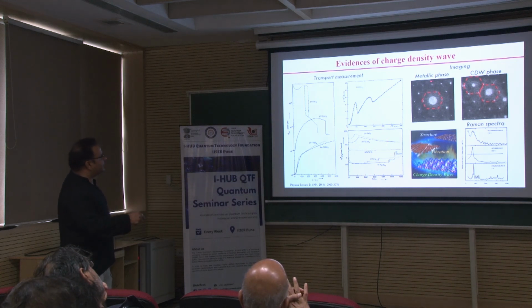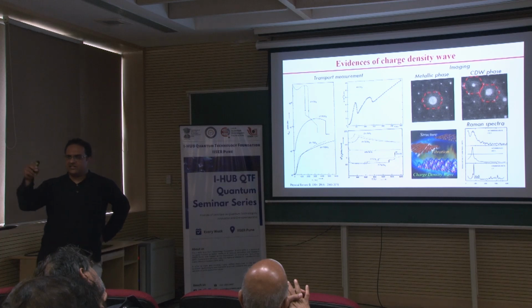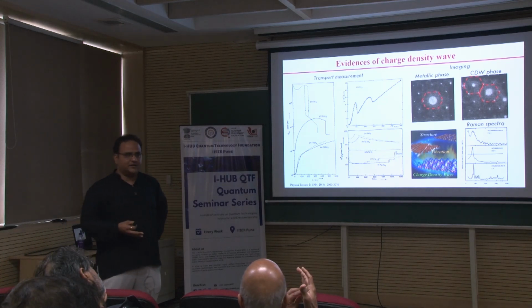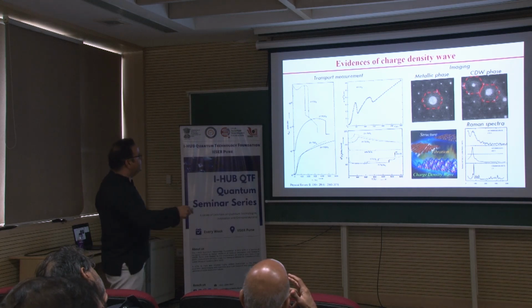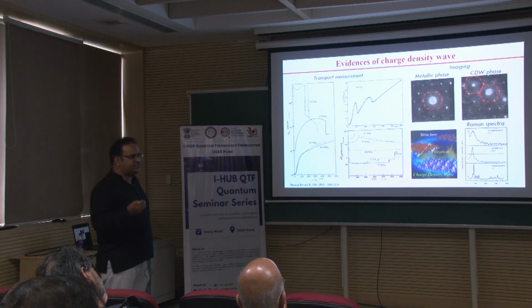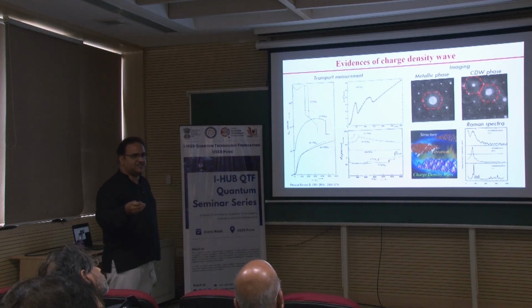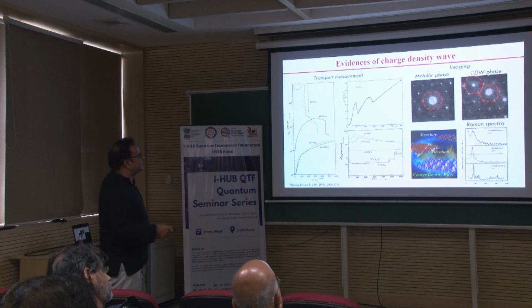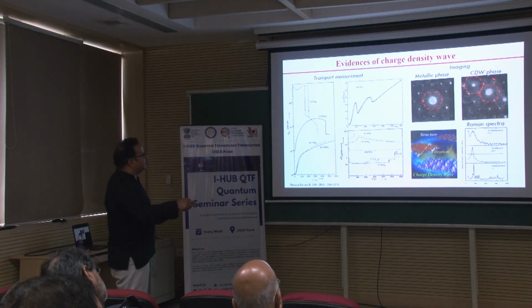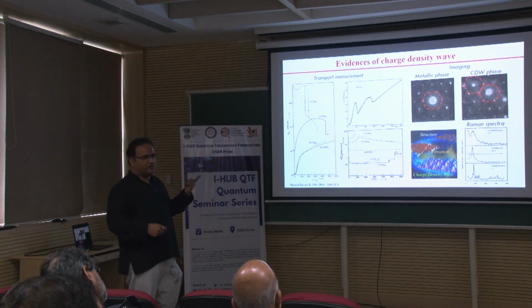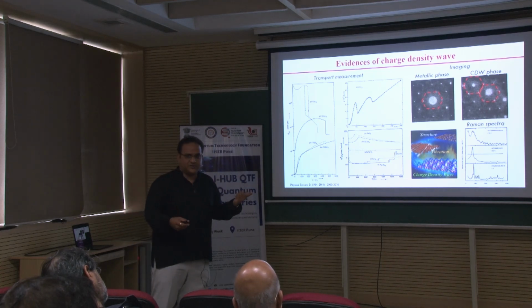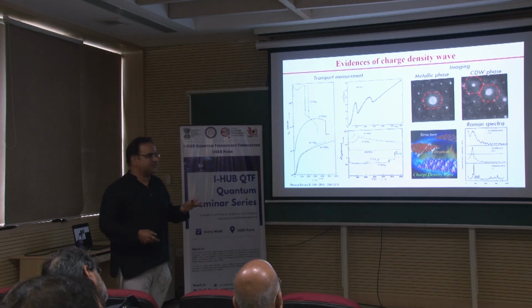Another evidence you can see is that you go to the charge density wave state and do transmission electron microscopy, or selected area electron diffraction. You will see that on top of the usual structure, you will see some signature of a new structure, which you call superlattice structures, which shows that this is the CDW state. And since electrons are involved and phonons are involved, there is a way: you do Raman spectroscopy, and you will get the signature of the charge density wave as well.